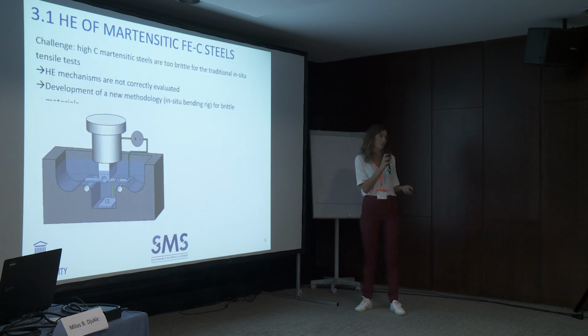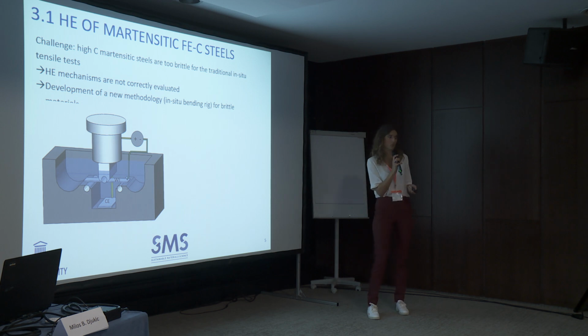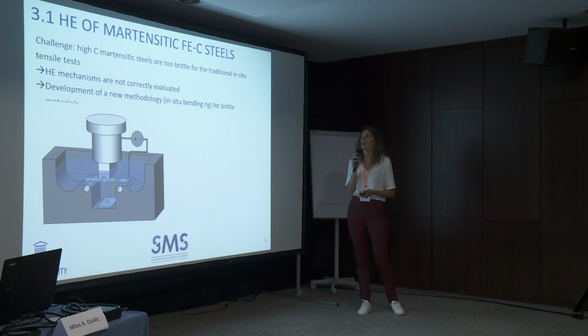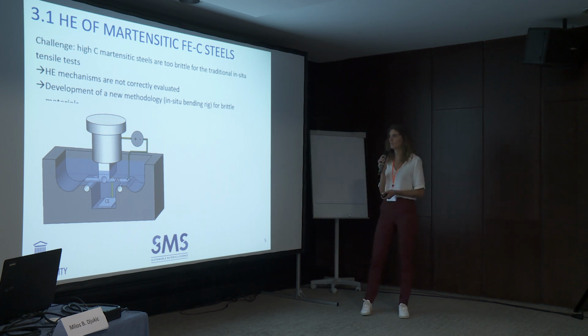However, another important challenge I endured during my PhD is that high carbon martensitic steels are way too brittle to be tested by the traditional in situ tensile testing. Therefore, the hydrogen embrittlement mechanism of brittle materials is often not correctly evaluated, and therefore I developed a new methodology, namely an in situ bending rig for brittle materials.